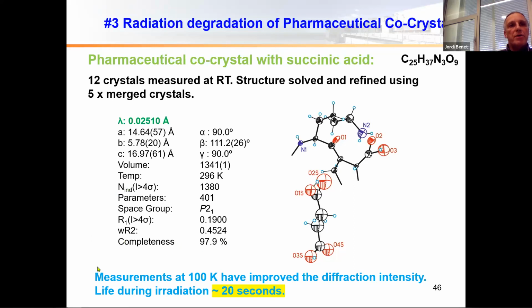Later on, we tried also to measure the same sample at 100 Kelvin, and although the damage by radiation cannot be avoided, these crystals were surviving a bit longer, 20 seconds maybe. But there was another point which was important. At 100 Kelvin, the crystals diffracted much stronger, so that we were able to collect a better data set, so that we have also better statistics of this. They are not in this presentation, better statistics of the structure using, let's say, low temperature.